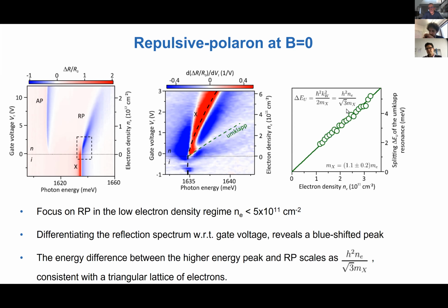If we monitor the density dependence, we find that it falls on a line that is determined by an exciton mass of 1.1, which is a bit smaller, but within the error margin of our experiments, agreeing with the center of mass of the exciton and consistent with the triangular lattice. Okay, so that is good.